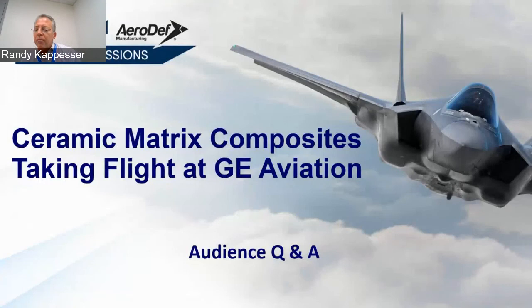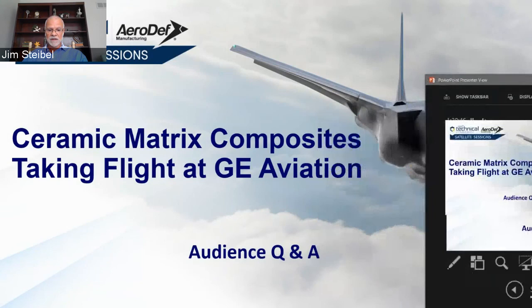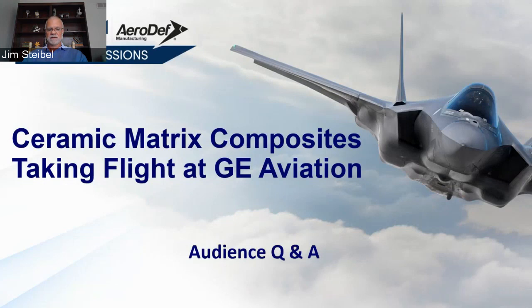From Babak, what type of tools are used for CMC layup, and how are those tools generally manufactured? Yeah, that's good. We look at pretty traditional tooling materials, and there are forms of steel and aluminum that work well. You're trying to match the CTE, coefficient of thermal expansion, but at the same time, you want something that will respond thermally and yet be producible. For the second half of your question, we can do things with additive manufacturing to make cheap, complex metallic tools. We can do more traditional machining hog-out methods. A lot of times that's typically what's done. But yeah, it's some combination of those.